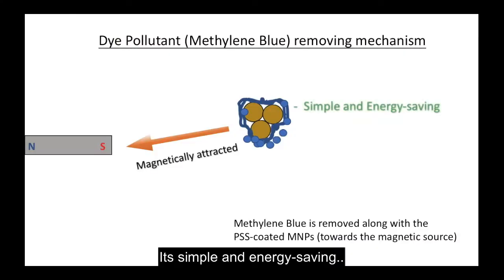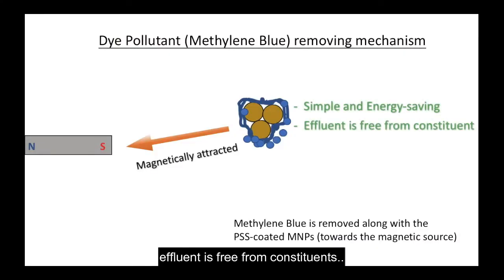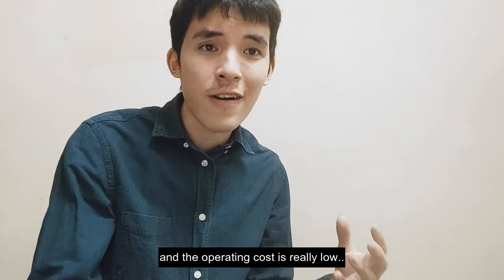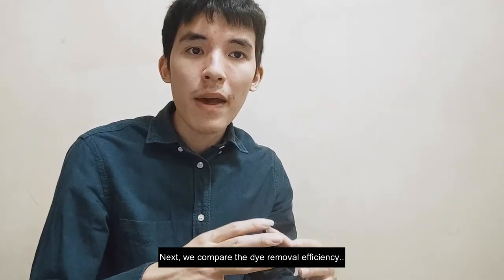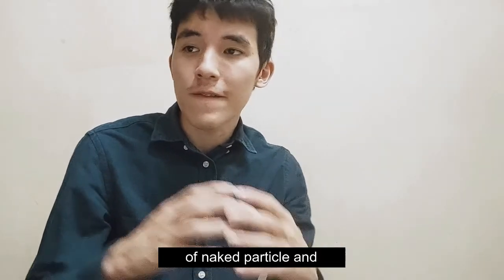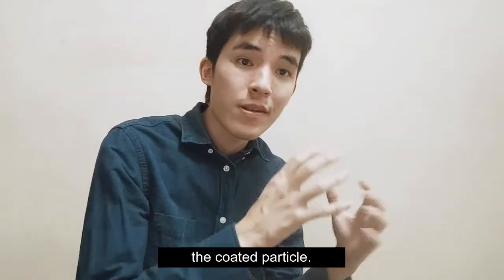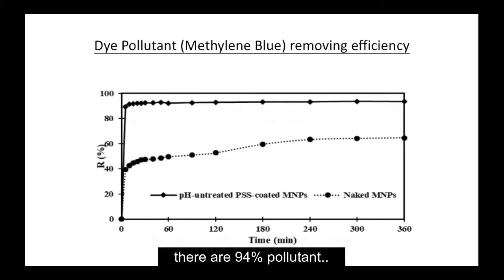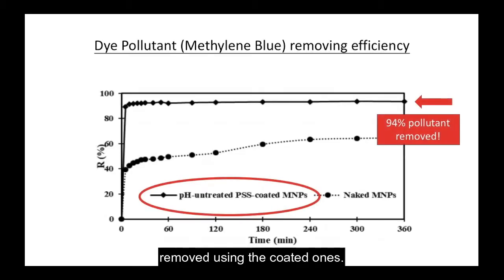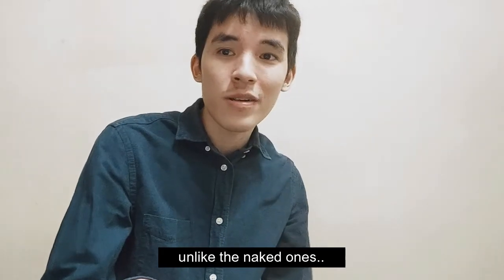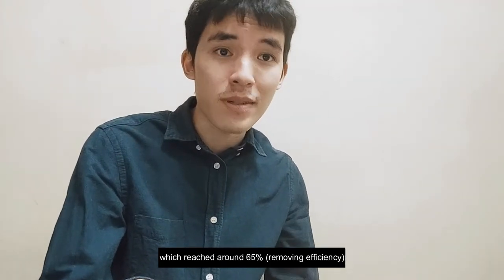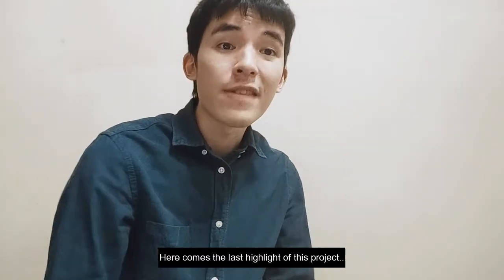It's simple, energy saving, the effluent is free from these constituents, and lastly, it's really cheap and the operating cost is really low. Next, we compare the dye removal efficiency of the naked particles and the coated particles. As our results show, 94% of pollutant is removed using the coated ones, unlike the naked ones, which reach around 65%. Here comes the last highlight of this project.